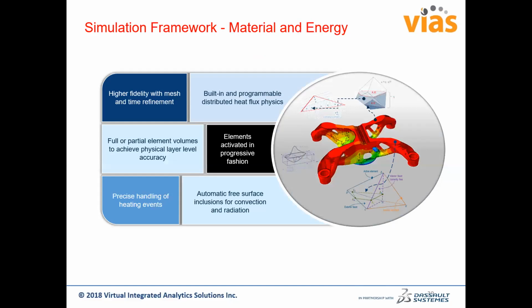But as I mentioned, due to partial element activation, your mesh doesn't have to exactly follow your time point of interest and your spatial domain of interest. So you can have a relatively coarser mesh, but within one model you can have finer mesh at some points and coarser mesh at others. This will bring down the total computational time significantly, and this entire process is automated. All you have to do is designate certain areas and put in some parameters for the simulation, and all the modeling, all the meshing, is done automatically.